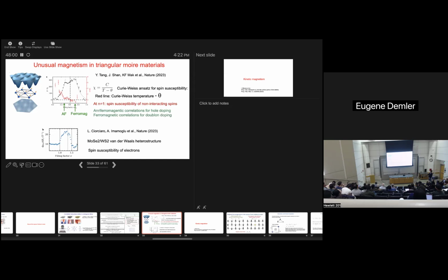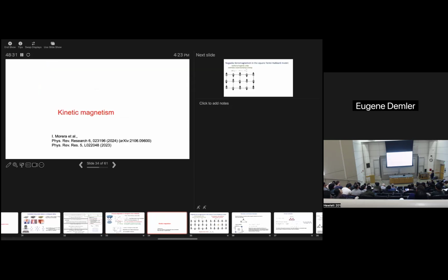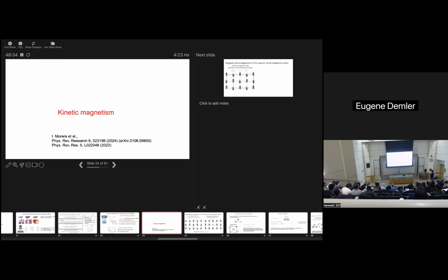And then similar experiments were done in the group of my colleague, Atac Imamoglu. So they do not see antiferromagnetic correlations on the hole doped side, but they see very strong ferromagnetic correlations on the other doped side. And they also see that there are no interactions. Effectively, we have decoupled spins exactly at half filling. So very distinct behavior from what we saw in the case of square lattices. Okay, so I want to explain what is the new, different type of magnetism that has been seen here.